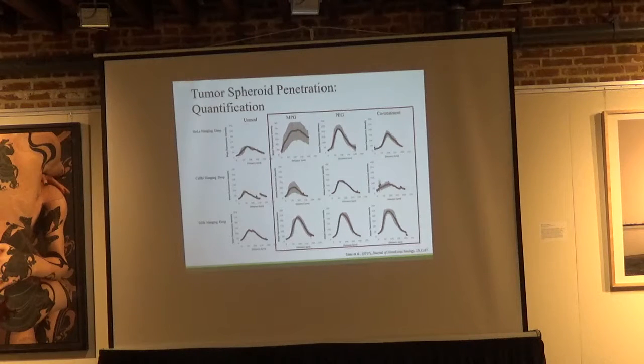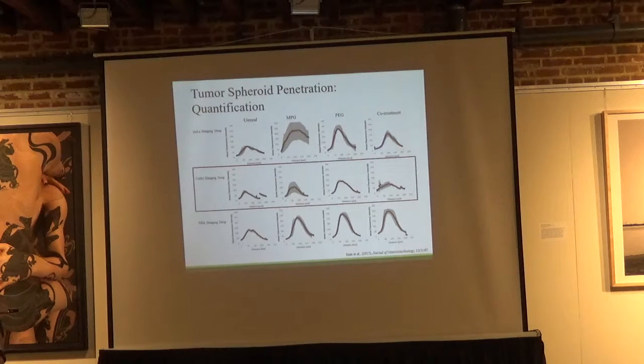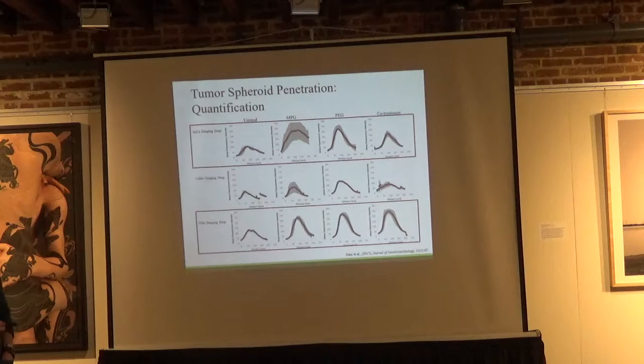And one trend that we found in general is that modification of the particles, whether it's MPG, PEG, or the two particle groups delivered together, all provided increased uptake and penetration into these tumor spheroid areas. We also noted that while HeLa and SiHa provided moderate uptake and penetration, CaSki, which are very tight tumor cells, provided very little room for the particles to get into the tumor matrix in comparison to the HeLa and SiHa